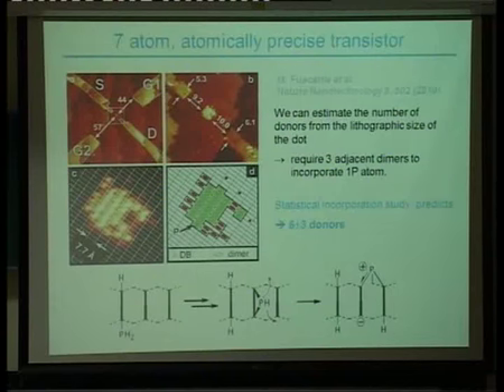So now we're trying to understand what gives rise to those resonances that I showed you in the stability diagrams. So we're making our devices much smaller now. So we've reduced the size of the central dot, where we know, from the exposed area, that we have 3 adjacent silicons to get 1 phosphorus atom in. We have basically 6 plus or minus 3 donors in this small quantum dot structure that I'm showing you.